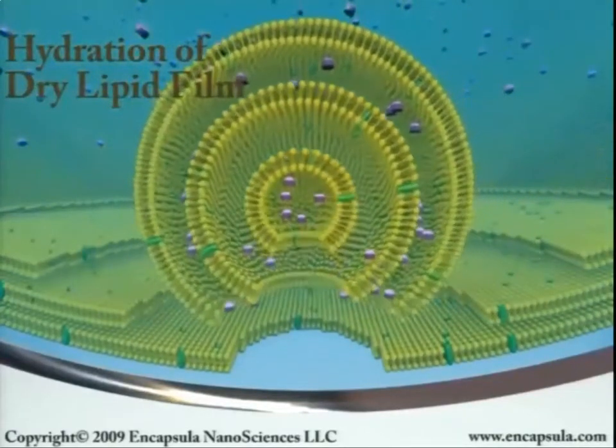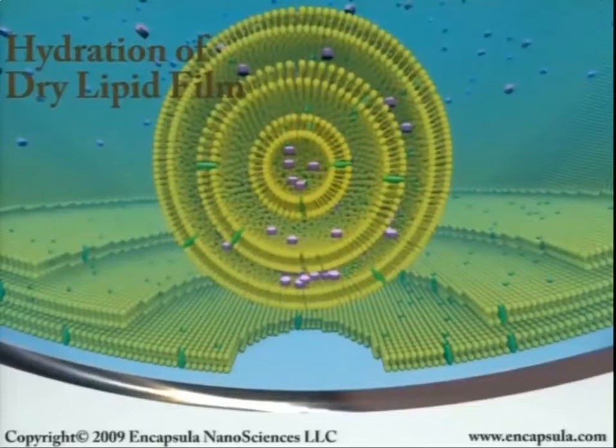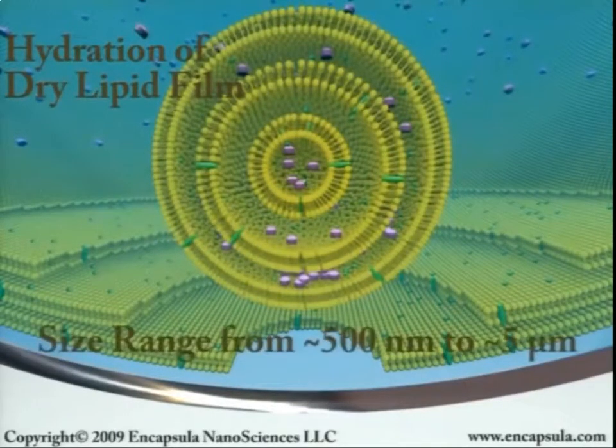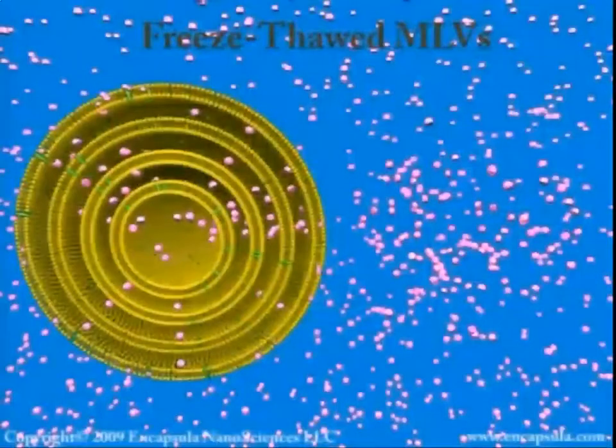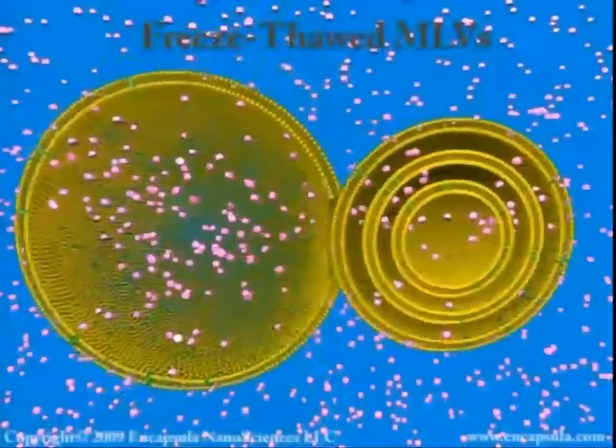While all or most of a lipid-soluble compound will be incorporated into the bilayers of these liposomes, the amount of water-soluble compound entrapped is usually very low because these MLVs have a small captured volume. Very little aqueous solute penetrates the onion-like layers of hydrated bilayer lipid. The captured volume of these MLVs can be increased by freezing and thawing the liposomes several times.